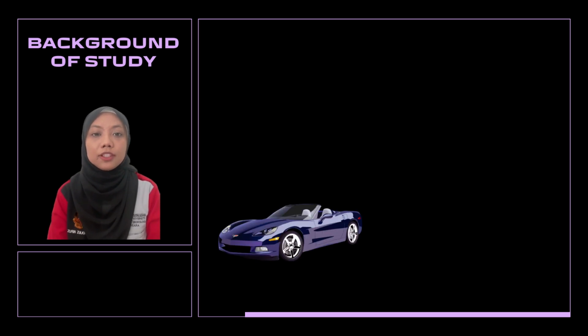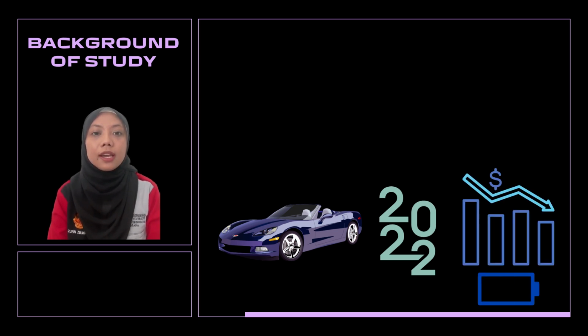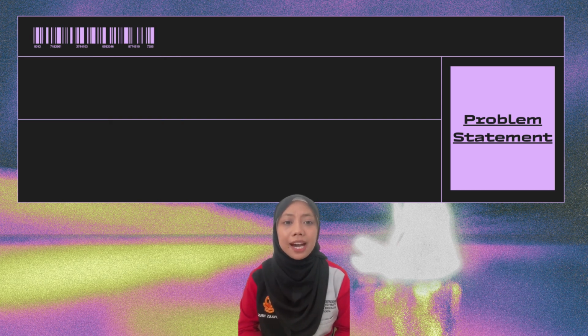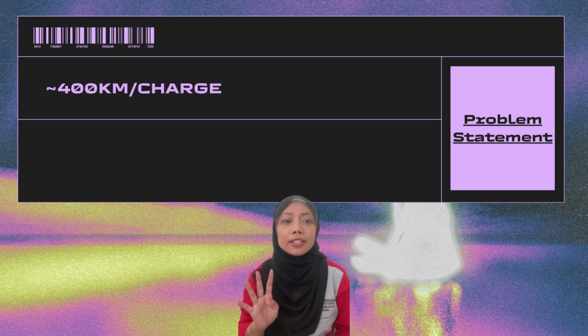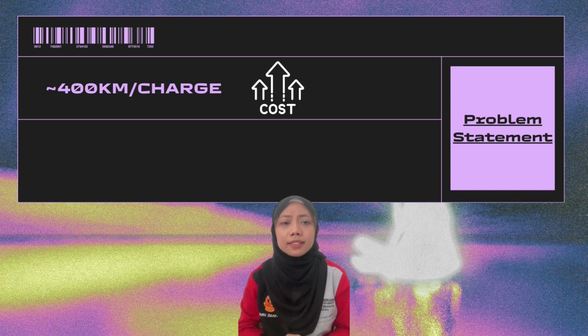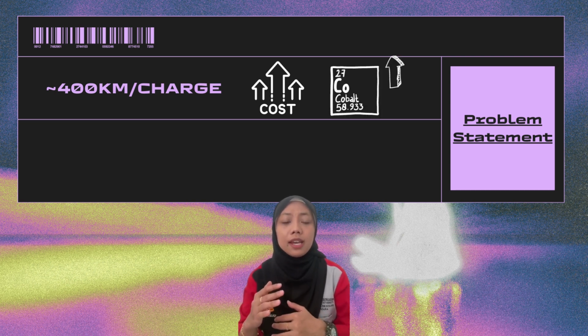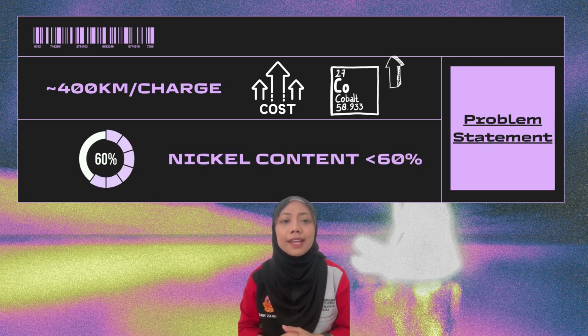According to Bloomberg, electric vehicles will become equally affordable with conventional cars as early as 2022 as the cost of batteries declines. Energy capacity for current commercialized lithium-ion battery in EVs is still not enough, where it only has a driving range of 400 km per charge, and the costs are still high due to higher cobalt content in lithium-ion battery. Till now, cathodes with nickel content of less than 60% are fully commercialized, and this is still not good enough for the EVs industry, where they need a higher energy density.